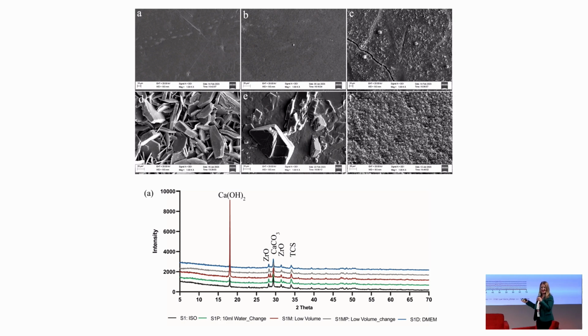When we test solubility, we weigh things, and we weigh things in water. The human body is not water. The human body is salts. So essentially, if you're weighing and you have a salt, anything which is deposited on the surface is weighed. If you put it in water, there are no salts on top, and obviously it weighs less. Okay, so very, very important, we don't go overboard with the question of solubility.